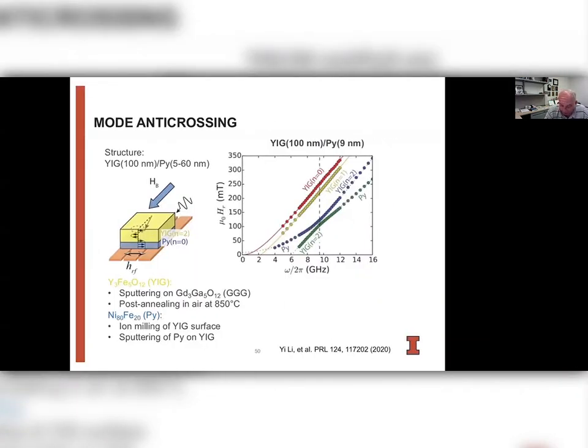And indeed, this is what we see here. This is now the resonance field as a function of frequency for our 100 nanometer thick yttrium iron garnet, 9 nanometer thick permalloy bilayer. Here you see the homogeneous ferromagnetic resonance mode. Here's the first order spin wave mode, and this is the second order spin wave mode, which crosses over with the homogeneous ferromagnetic resonance mode of the permalloy structure here. So we get a crossover at roughly about 10 gigahertz.